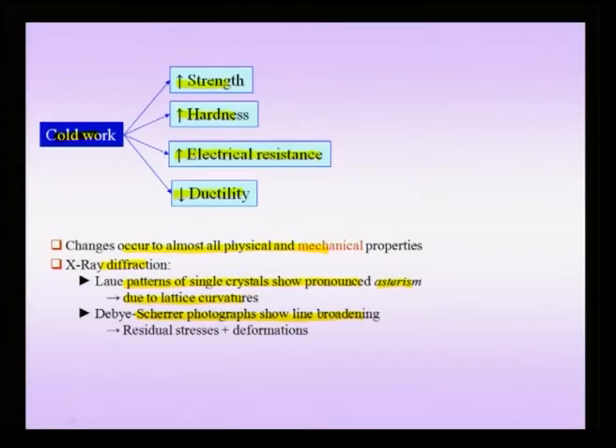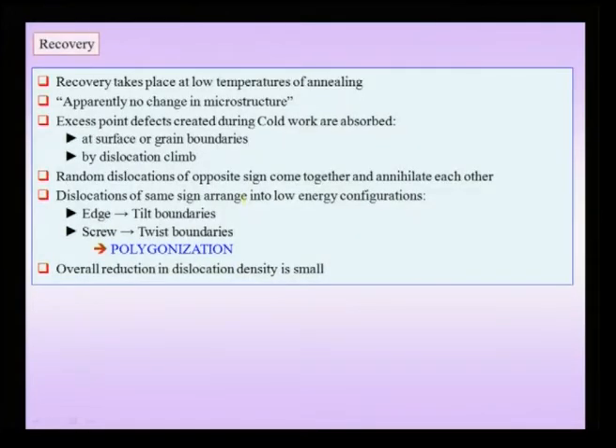So, cold work changes many of the physical and mechanical properties, which include the strength, the hardness, the electrical resistance and ductility, and if you do annealing, you can reverse this and get the material back to its original well annealed state. Now, what does this term recovery mean? Recovery takes place at low temperatures of annealing, and if you look under an optical microscope, and not, for instance, a high resolution transmission electron microscope, but in an optical microscope or even a scanning electron microscope, you would note that there is apparently no change in microstructure.